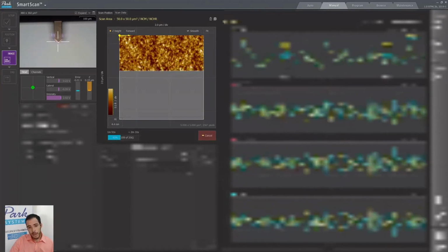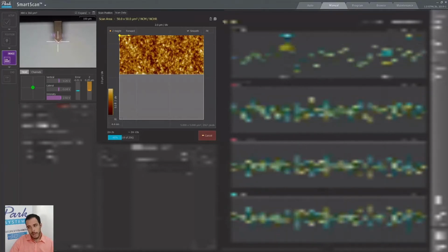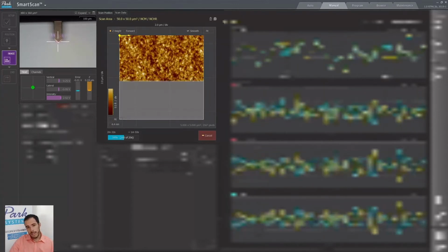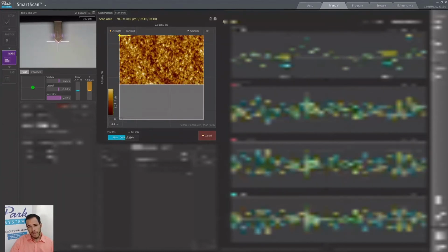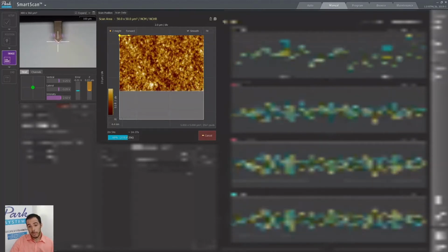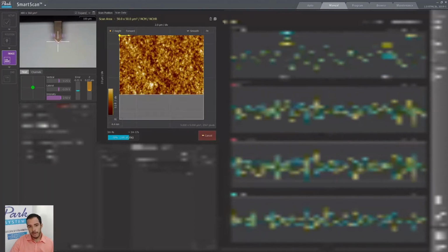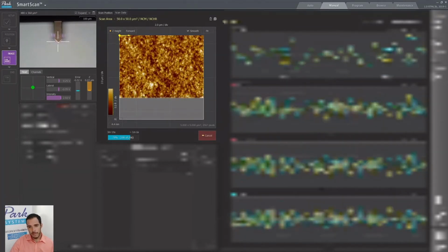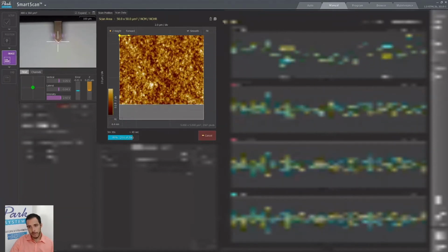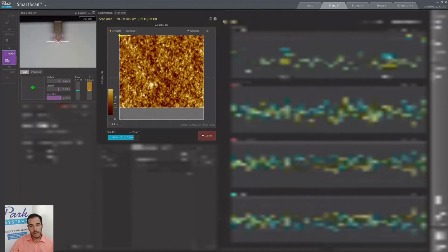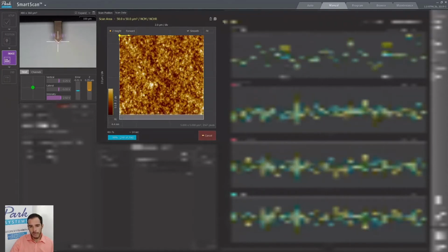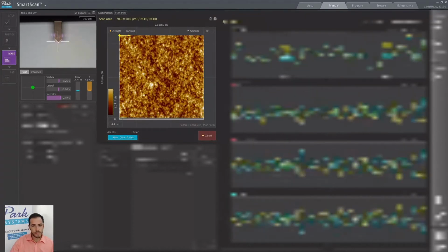Also, this is a compact disc, so it's a polycarbonate film, which is very delicate for stiff or medium-stiff cantilevers. In this case, I'm using an NCHR cantilever. Therefore, if I try to scan with this cantilever, I'm probably going to scratch the surface of the sample. My other option would be to use a softer cantilever to scan this image. But as I actually want to do a scratch over my sample, that's why I'm also using non-contact mode. If I look at the topography, we can see we're going from a couple of angstroms to a maximum of 10 nanometers, with a relatively smooth surface.